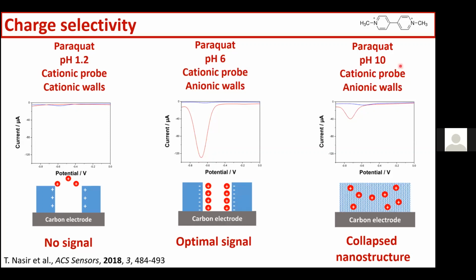And then if we increase the pH above 8, and here is an example with pH 10, we still get a signal at the modified electrode, but it's shifted to more negative potentials. So it suggests that it's more difficult for the redox reaction to occur, and the signal is lowered compared to pH 6. What happens is that we're starting to have some dissolution of the silica walls, and then we're losing part of our signal. So if we want an optimal signal, we should be between pH 6 and 7, to be sure that we have negatively charged walls and that we don't start slowly dissolving the silica films.